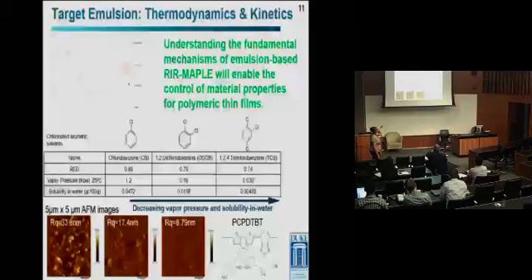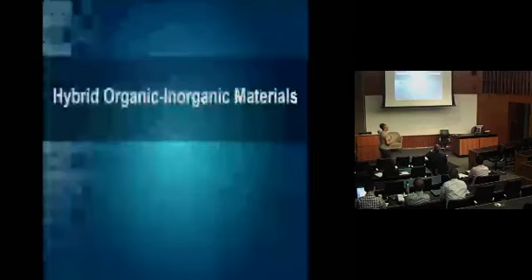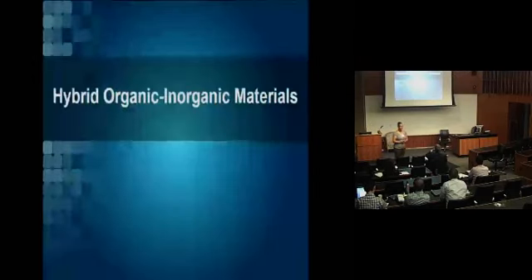So as an example, if we change the primary solvent for this polymer, PCPDTBT, which is a low band gap polymer used in solar cells, as we change the primary solvent and the properties of the primary solvent changes, we get these very different surface roughnesses on the film. So going from 33.8 nanometers root mean squared surface roughness to about 8.7 nanometers, just from what the primary solvent is. So this type of effect is something we're trying to understand better. So that's a brief introduction to emulsion-based RIR-MAPLE.